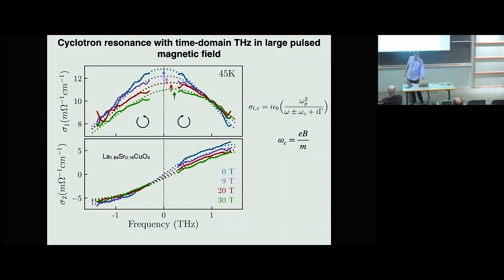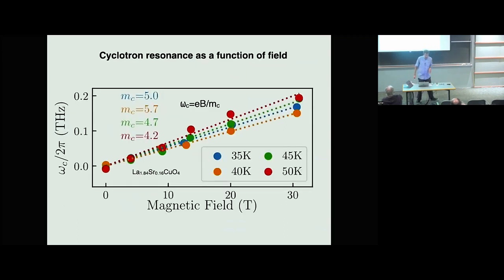Okay, good. So we can take data like that. We can pick out those peaks there. We fit the data, actually. And that's plotted here, cyclotron frequency as a function of the magnetic field at a bunch of different temperatures. And there's some funny temperature dependence in here that's small that we don't understand yet, and I'm not going to concentrate on that. You can see it's kind of non-monotonic. There's the 50K point, 45K is there, and then it comes down to 45K, 40K, backed up to 35. I don't understand this temperature dependence, but it's something that we're very interested in.